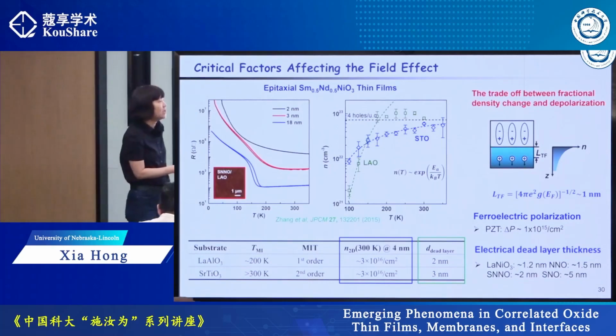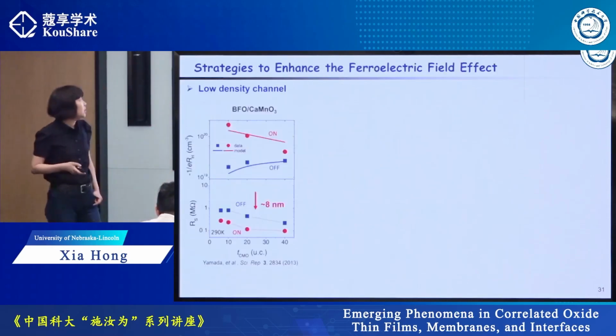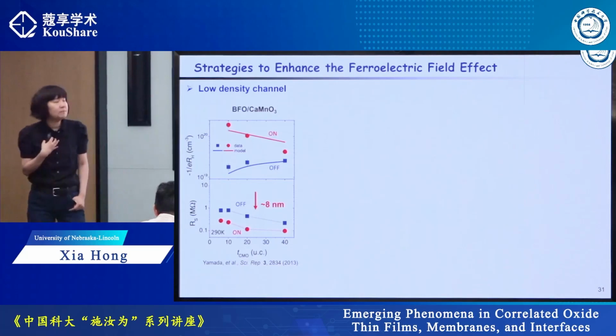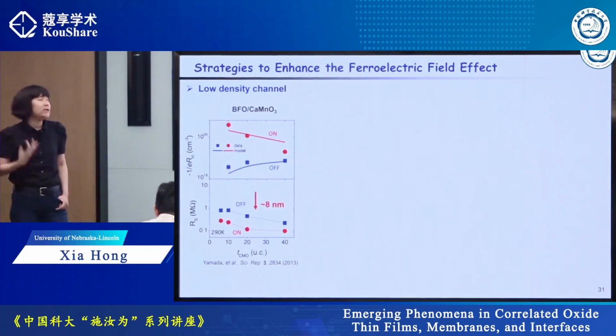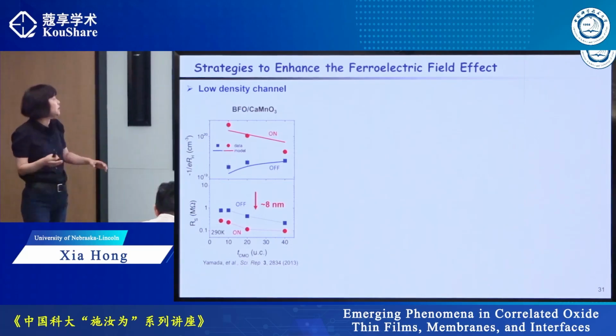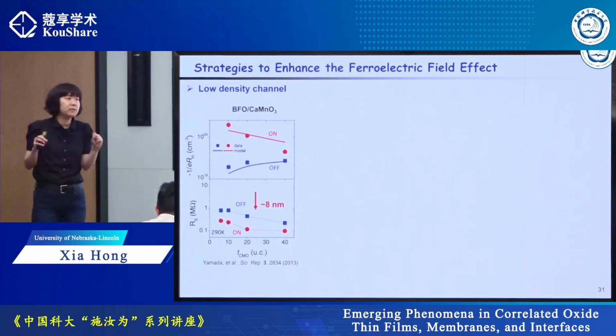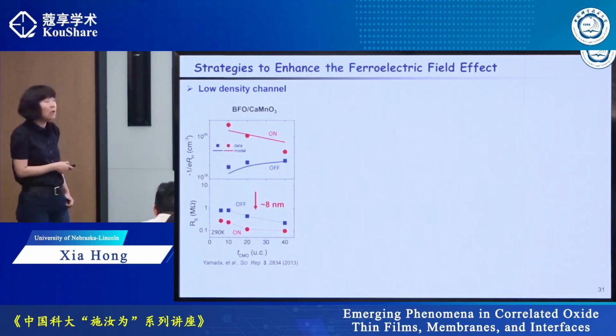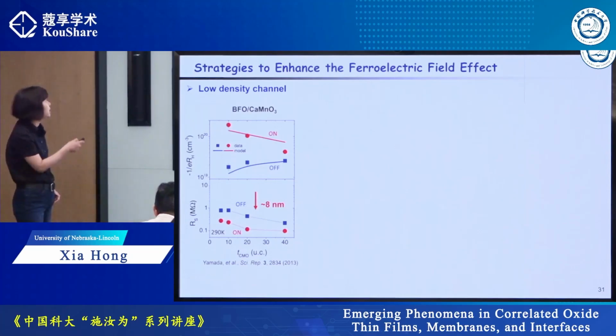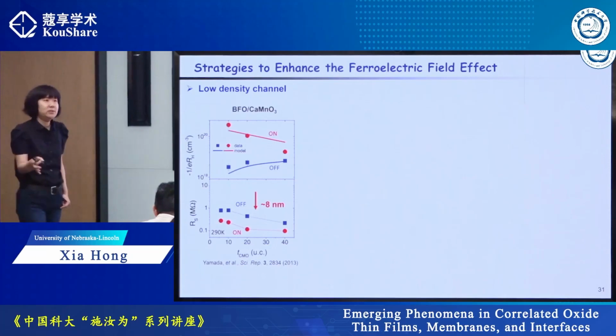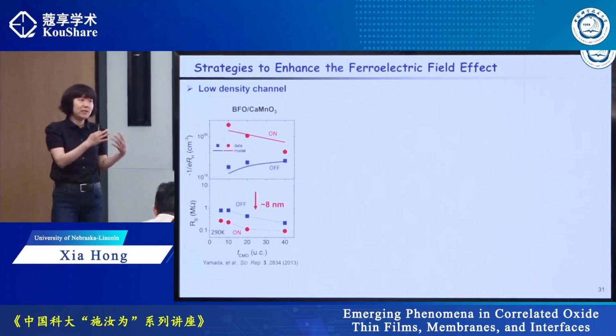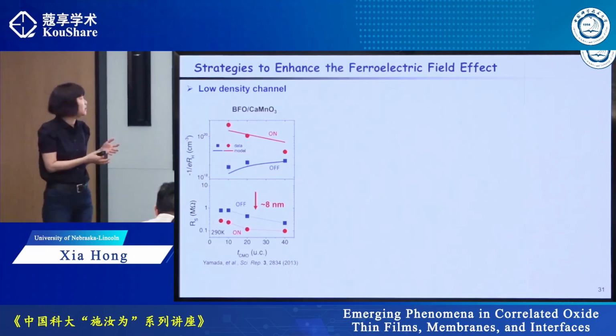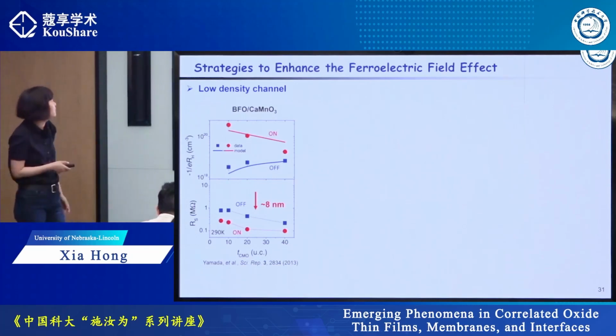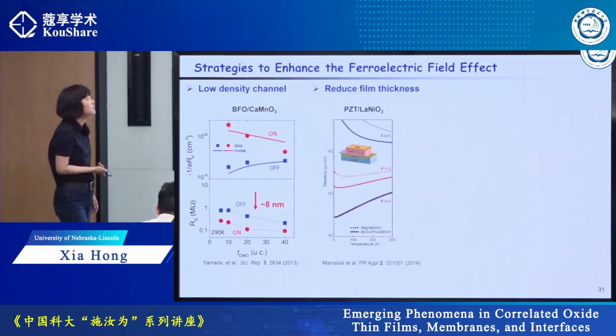So the more metallic the material is, the smaller the film thickness. So let's compare our approach with what has been done in the literature. Basically, people are tackling the problem using two approaches. One is working with intrinsically lower carrier density. But we just want to work with high carrier density material to reduce the short channel effect. So this defeats the purpose.